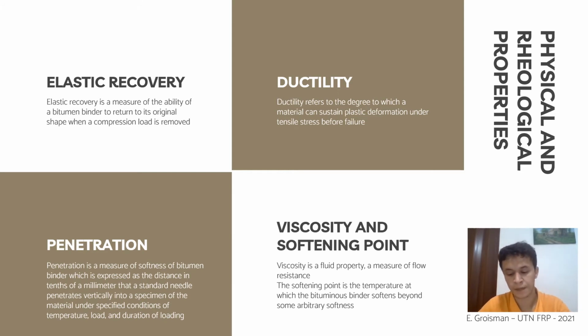And finally, the viscosity and the softening point. As I mentioned, bitumen is a viscoelastic material which doesn't have a sharply defined melting point. What does this mean? That its viscosity starts to decrease as we increase the temperature. So viscosity is a fluid property. It's a measure of flow resistance, whereas the softening point is the exact temperature at which the bituminous binder softens beyond some arbitrary softness. Well, what happens when we add crumb rubber? The softening point is increased and the viscosity also increases as the rubber content increases.